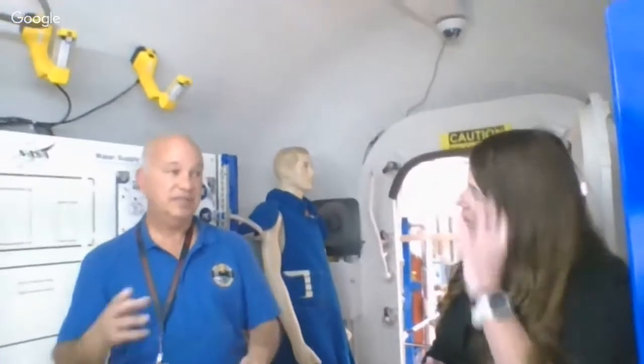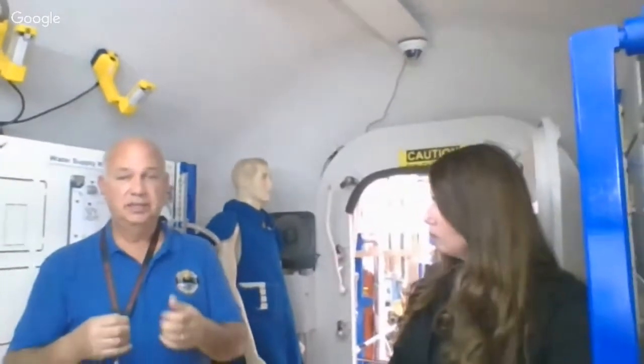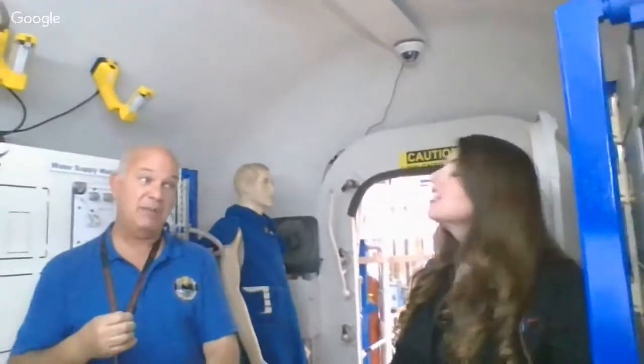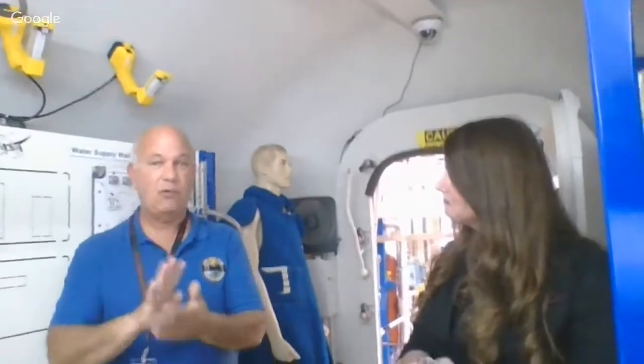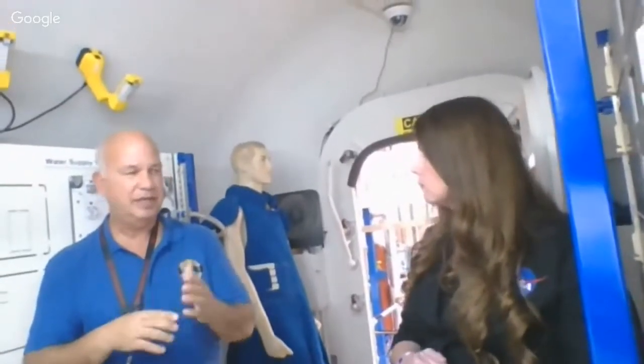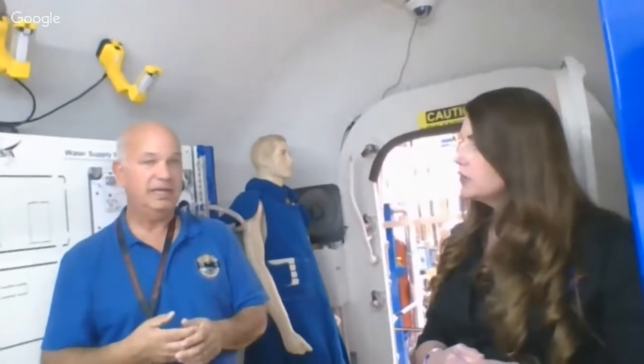Okay. So we have looked at several different materials for those straps, and we put on the weights that they can supposedly take. They handle that amount for maybe a couple of weeks, so they don't last the whole time holding that amount of weight. We're never going to be putting that amount on there. Like I said, it's a 4 times safety factor. We've gone down to 50%, and they lasted a couple months, and then we were in the range of 20 to 40% of what they said they can hold. And they've been lasting over 5 years. We also do cuts in the sides and cuts in the middle. They cut it in a vertical direction, and it has very little effect on the pre-tension.